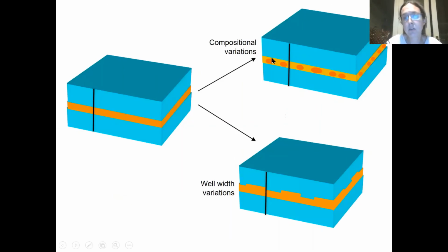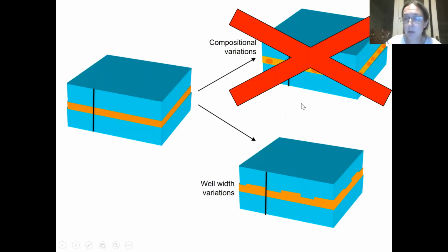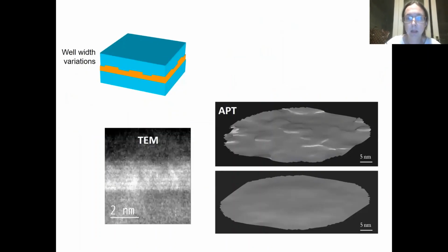Okay, so I said compositional variations were a possibility, but we can't find them in the atom probe, and we're very doubtful of the data in the transmission electron microscope. So what about these well width fluctuations, which I said were another possible way of trapping the electron in the hole? Well, we did find those, both in the transmission electron microscope and in the atom probe. If you look at this TEM data, you can hopefully see that the bottom interface of the quantum well is rather sharp and rather smooth, and the top interface is much more blurry and bumpy.